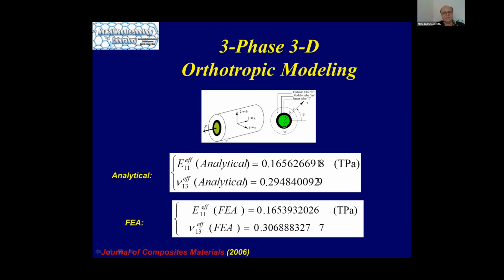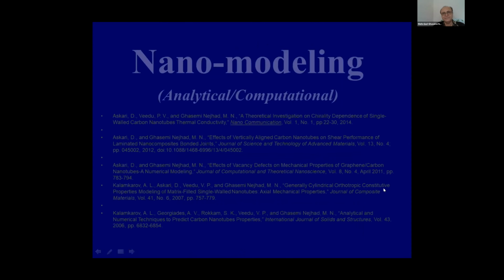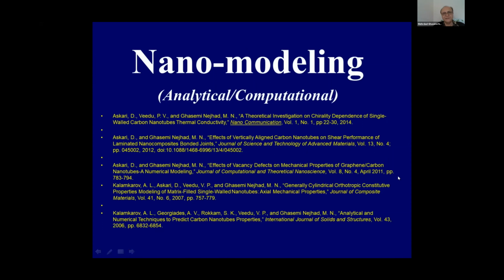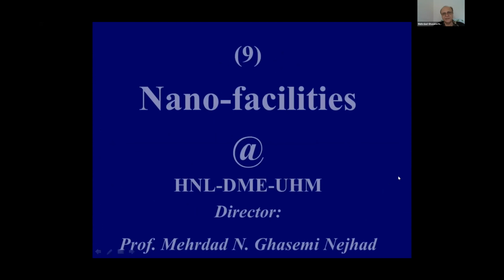Here again, we modeled a combined one. Here the black is a single wall carbon nanotube. You fill it with matrix inside and outside. So we had an analytical solution to find the effective properties, modulus and Poisson's ratio. Also finite element, and the results were very close, as you can see here. So here I have the list of publications for the different papers that I mentioned to you.